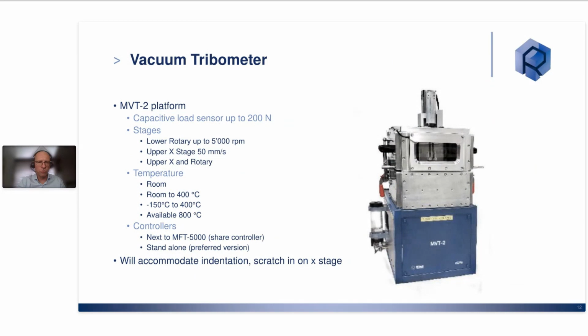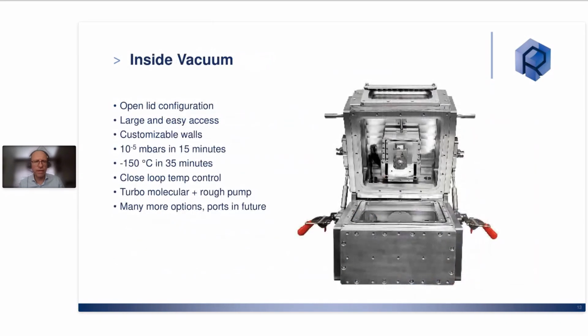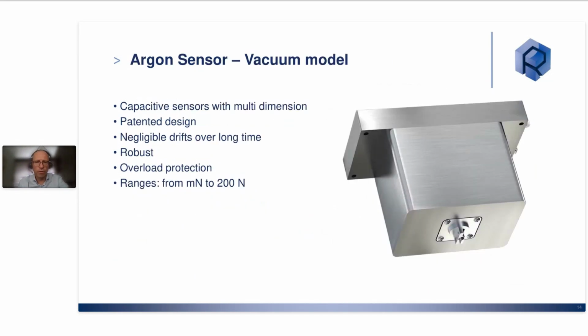And then it could be combined with different levels of temperature control in order to reproduce the real condition in the field. The interest of the vacuum system is the fact that we can have a force control where we could change the speed of rotation, we can change the load applied in order to be able to change the condition of testing without cutting the vacuum, meaning that you can change the condition of testing while doing the tribological test.